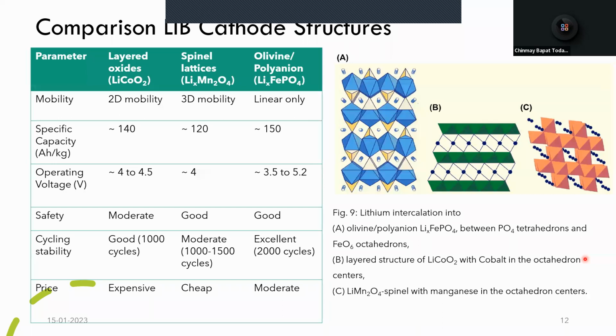When we include manganese and aluminum in their chemistries, they have a slightly improved safety, but the risk is not fully gone because cobalt is still there. When it comes to spinels, lithium manganese oxide is cost effective and safe with a potential of 4 volts versus lithium. However, they have the lowest specific capacity amongst these three materials, and they are limited in their longevity due to the dissolution of manganese into the electrolyte when the battery cycles. For olivines, they offer a stable chemistry with higher capacity than spinels, but they are limited due to their low potentials of 3.5 volts with respect to lithium. However, recent developments have incorporated nickel into the olivine structure, and it has led to an increased potential of around 5.2 volts, which is better for the battery operation.